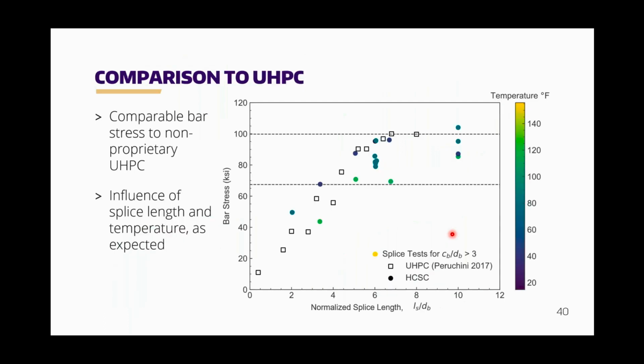And so we're able to take all of this data now and start to analyze it and start to come up with some conclusions. One of the first things we wanted to look at was how does this compare to non-proprietary UHPC? And so that's what we're showing you here. We have the peak bar stress on the y-axis, we have the normalized splice length on the x-axis, and I'm showing you the yield and ultimate stress of the reinforcement in our test case.